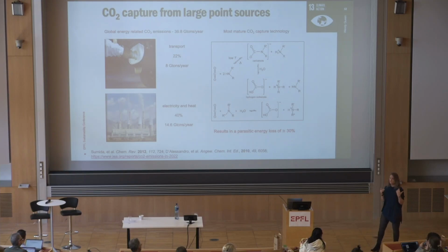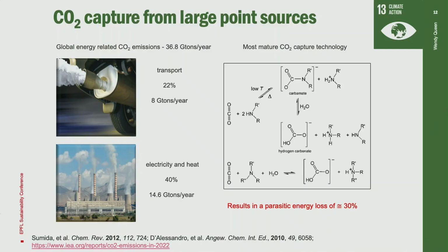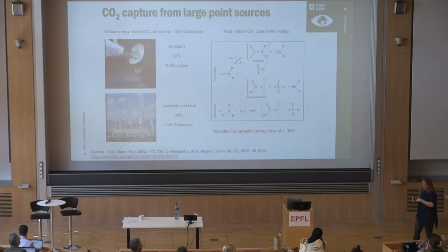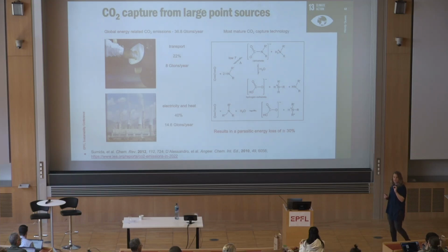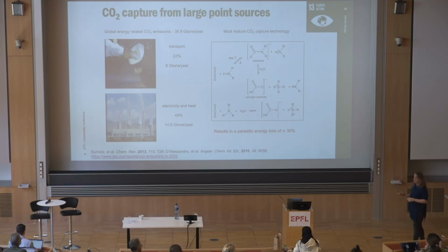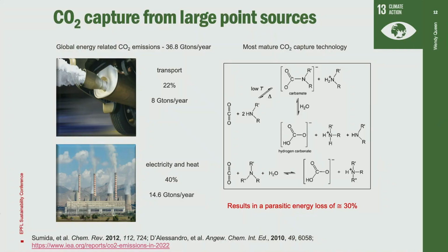Materials have really, really high heat capacities. This just means that you have to put a lot of thermal energy back into the materials to re-release the CO2, okay? This is the major issue with the energy consumption, is how much you have to put in to re-release the CO2. We also have degradation processes with the amines, among other things. So if you were to implement these at a power plant, it's effectively going to decrease your efficiency by a factor of about 30%.